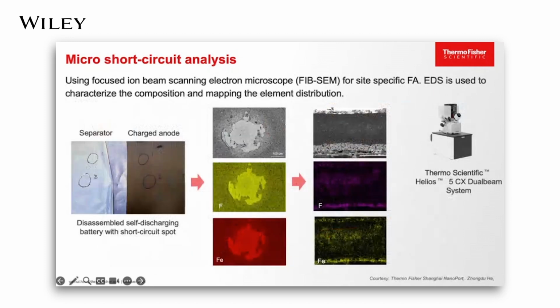I would like to share another use case for micro short circuit analysis with dual beam for a lithium iron phosphate battery. This was a high self-discharging battery, dismantled in a fully charged state. We did find the suspicious site of short circuit on the fully charged golden anode electrode. Then we cut across the site on the separator with dual beam and found the pores are blocked. The pores of the separator are blocked in a large area.